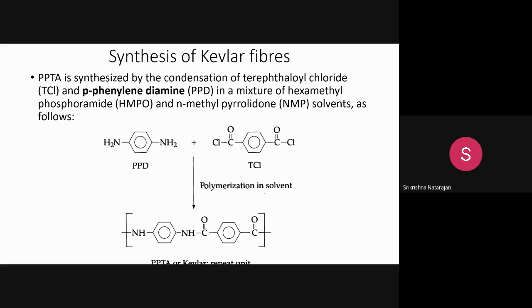You see how this fiber is produced. Similar to the method of Nomex fiber manufacture, we manufacture Kevlar also. Here, it is synthesized by condensation, which is a low temperature polycondensation, where a lower temperature is used. The precursors or raw materials used are PPD, which is paraphenylene diamine. You can see here two amine groups are there, but in the para position. It is paraphenylene diamine and terephthaloyl chloride. You can see here COCl, COCl. It is an acid chloride.